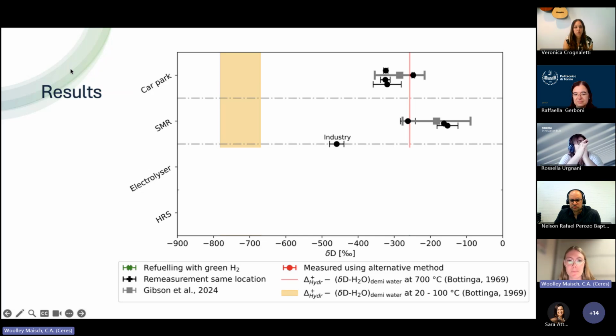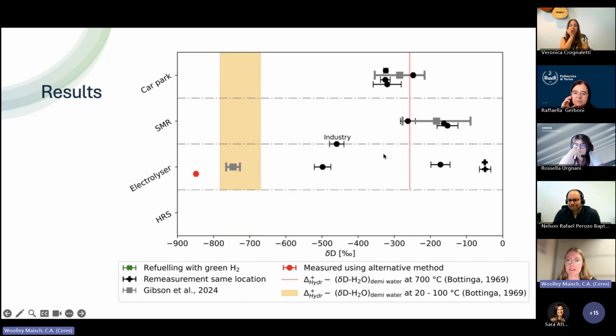And then the most interesting part now is that the electrolyzer, we expect it to fall in this orange range. That's the fractionation equilibrium for the water hydrogen at 20 to 100 degrees, which is the temperature at which electrolysis happens. And Gibson also expects the values to fall in line with this. However, we visited 4 electrolyzers and we see this really huge spread in source signature.